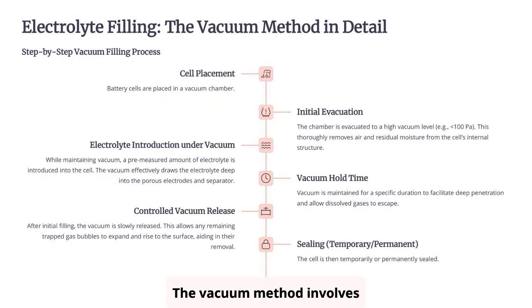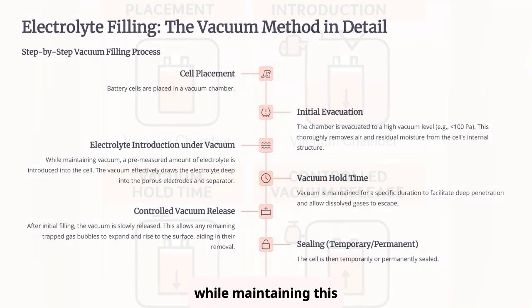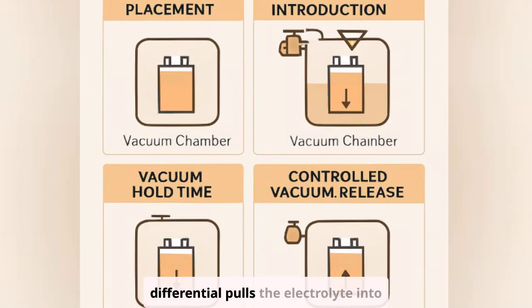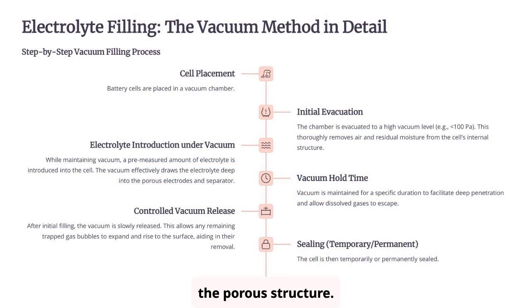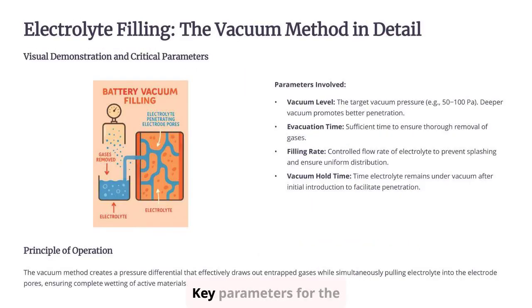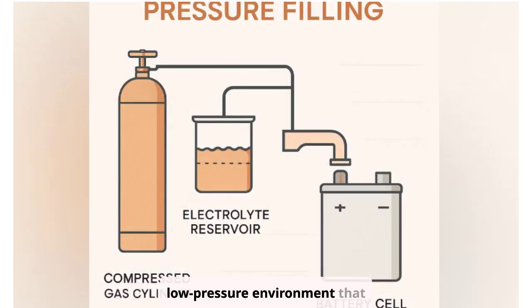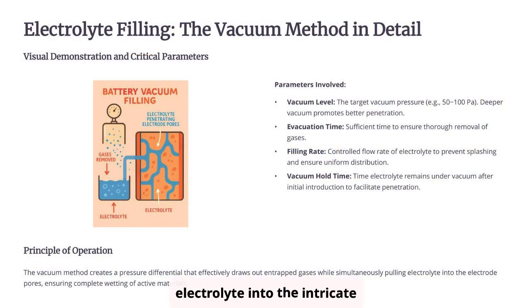The vacuum method involves placing cells in a chamber and evacuating it to a high vacuum level. Electrolyte is then introduced while maintaining this vacuum. The pressure differential pulls the electrolyte into the porous structure. A vacuum hold time allows for deeper penetration and gas escape. Key parameters for the vacuum method include the vacuum level, evacuation time, and vacuum hold time. The principle relies on creating a low-pressure environment that effectively draws out entrapped gases and pulls the electrolyte into the intricate pore network of the electrodes and separator.